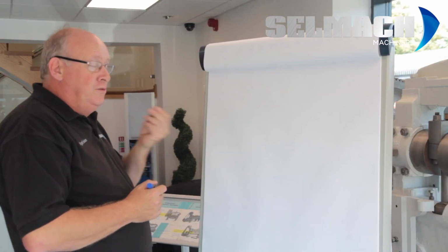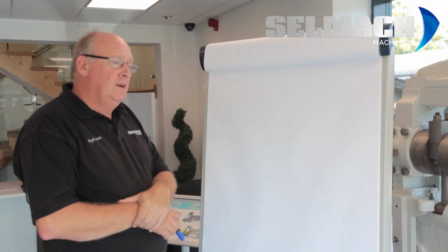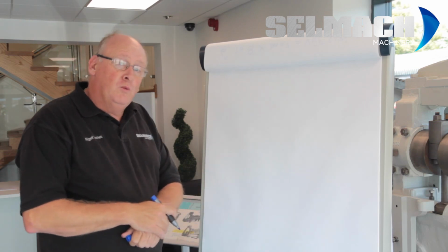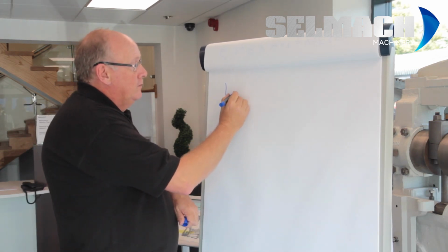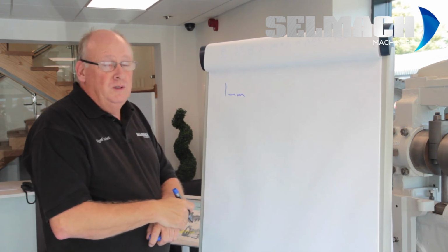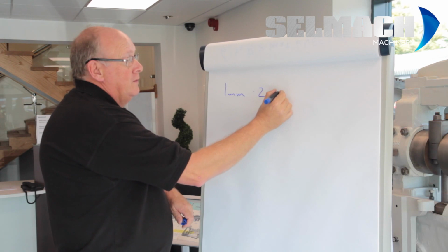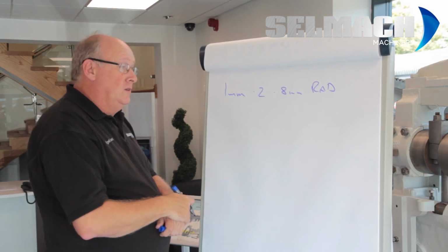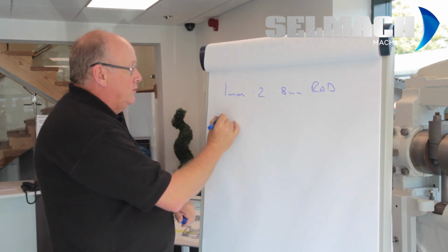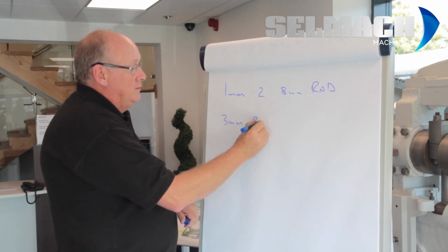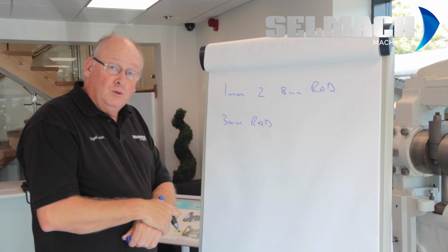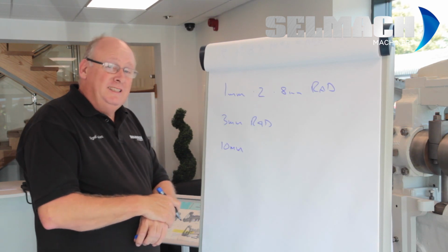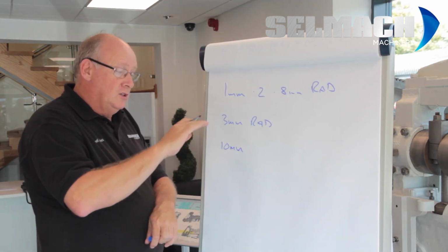Simple. Once you've worked your V size out, you need to understand the correct radius on the top tool that must be used. So, if we are folding 1 millimeter, a 0.2 to a 0.8 rad would be plenty. When we're folding 3 mm, you're going to be needing something like a 3 millimeter rad. Let's say you want to fold some 10 millimeter plate. You're going to need at least a 6 millimeter radius on the nose of your tool.